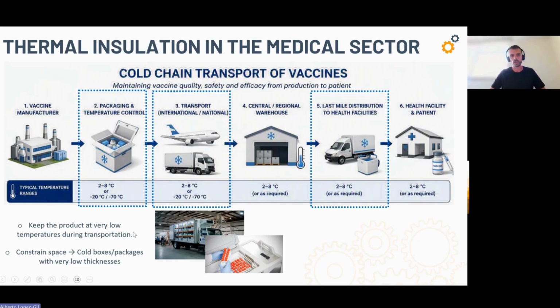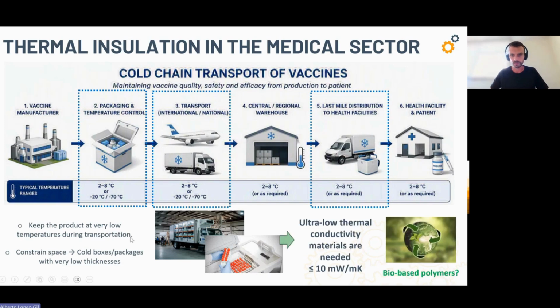And this is not the case in other applications for thermal insulation where we can play with the thickness to increase the thermal resistance. So it's clear that in this application concretely, and in general in the transportation of refrigerated products, generally vaccines, remedies, we need ultra-low thermal conductivity materials, allowing us to have lambdas below 10 milliwatts per meter Kelvin. So we believe in this case, the cost is not such a high requirement for the polymer or for the foam. So maybe this is an opportunity for bio-based polymers.